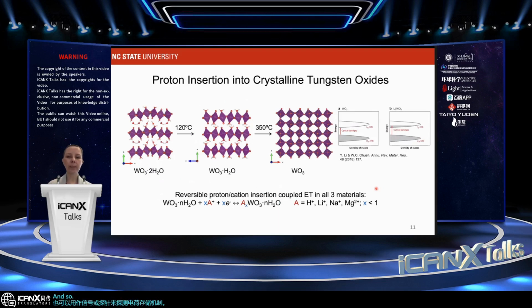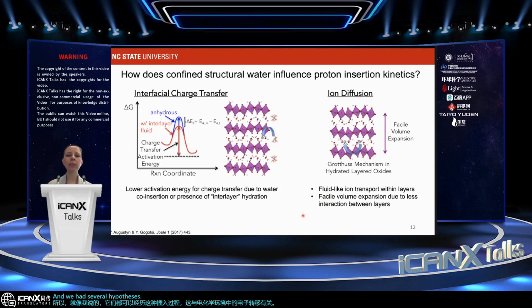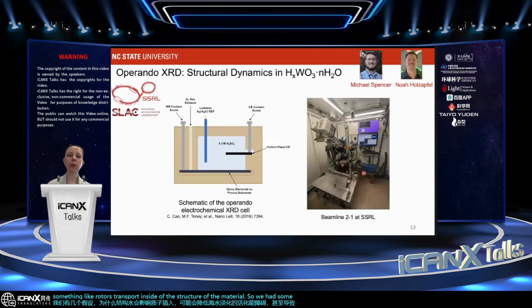And so one of the things that we're interested in when I first started my research group is to compare proton insertion into 3 different kinds of crystalline tungsten oxides. Ones that were layered structures that also contained water molecules, and the anhydrous structure that was a 3-dimensionally interconnected material. And so, like I said, they all can undergo this kind of insertion process that's coupled to an electron transfer in an electrochemical environment. And we had several hypotheses about why structural water could influence proton insertion, perhaps lowering the activation energy barriers for desolvation, or even leading to something like Grotthuss transport inside of the structure of the material. So we had some hypotheses about what could happen.